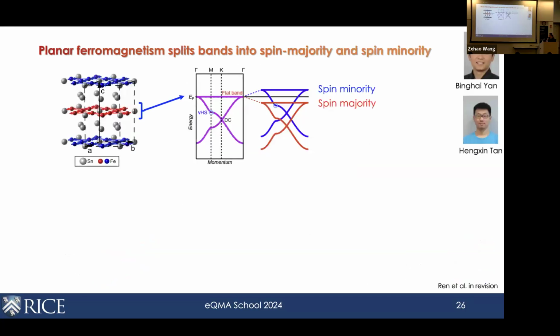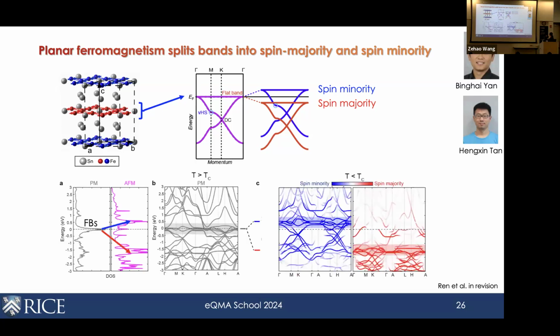Okay, so now onto our own data. So why should we understand the system as a ferromagnet? The way we look at this is that, remember, every layer Kagome sheet is ferromagnetic. What that means is that within that sheet, we can consider the bands should split into the spin majority and spin minority bands as the moments order. And then it's just the character of the spin up versus spin down that changes as you go across the layers, right? So with this in mind, we collaborated with Binghai Yan's group and also Hengxin Tan, who performed the DFT calculations for us on this system.